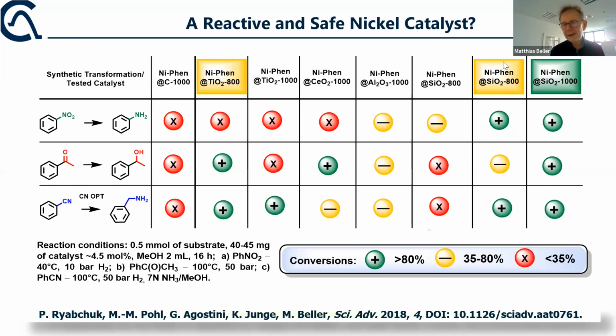So what we did is we prepared a number of specific heterogeneous materials which we thought could be active in hydrogenation catalysis. Then we chose three types of model reactions which are typically known to work well with the Raney nickel catalyst, and we studied the different material behavior for these model reactions. An important point in replacing classical Raney nickel is to look not at only one catalytic transformation, but at several, in order to have a general replacement. The only material among many others, which are not shown on this slide, that was able to do reactions with similar efficiency to Raney nickel is this specific nickel catalyst: nickel nanoparticles supported on silica.